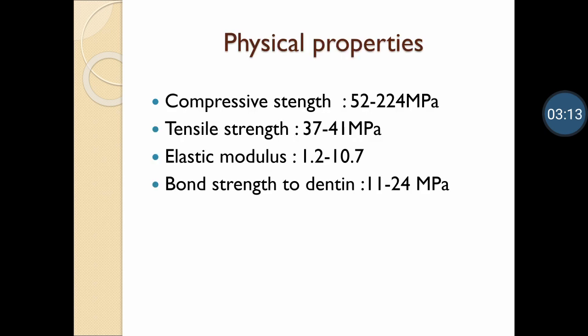The physical properties here include a compressive strength of 52 to 224 megapascals, which is sufficient to withstand the occlusal forces from the overlying prosthesis. The tensile strength is 37 to 41 megapascals, whereas the elastic modulus is 1.2 to 10.7. The bond strength to the dentin is 11 to 24 megapascals. As these resin cements, unlike other cements, micromechanically bond to enamel and dentin, the bond strength to the tooth structure is very important to withstand the occlusal forces received from the overlying prosthesis.